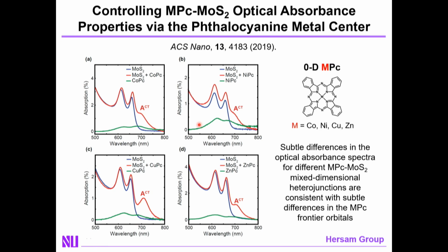Now, as I alluded to, the beauty of organic chemistry is that we can now look at a whole series of such heterojunctions just by changing the metal center and the metallo-phthalocyanine. For example, looking at the series cobalt, nickel, copper, and zinc. I'm not going to walk you through all of these spectra in great detail, but just by eyeballing them, you're going to see that there are clear differences in the nature and wavelength of the charge transfer state, and this can be explained by differences in the frontier molecular orbital energetic location with respect to the band structure of the 2D molybdenum disulfide.